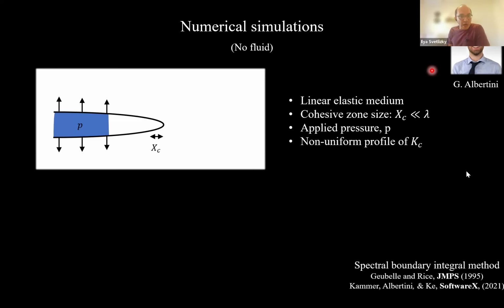So again, following our analysis that I showed you before, we said, okay, let's ignore the fluid and mimic it just by the pressure it applies on the crack faces. So the setup that Gabriele did is a linear elastic medium. It's a brittle crack. The cohesive zone size is finite, but very small, at least relative to the lag. The pressure is prescribed. I think Gabriele took a constant pressure profile, but it doesn't really matter.